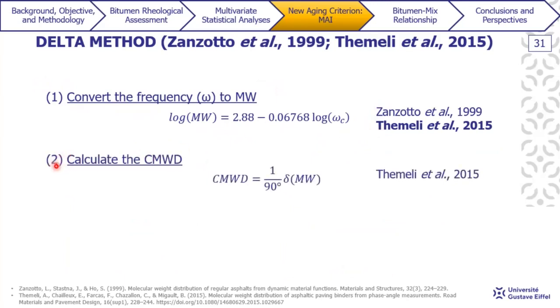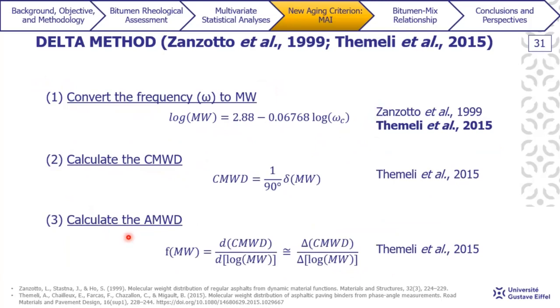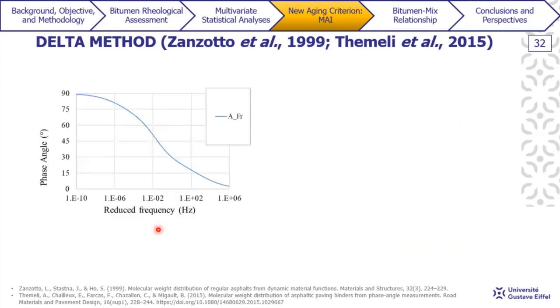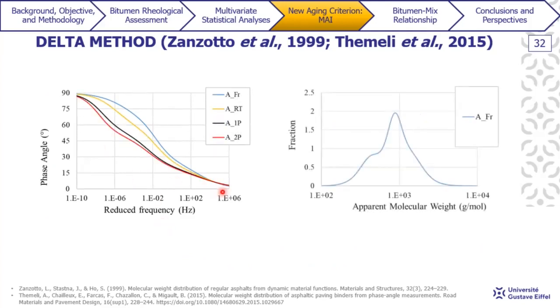Then we calculate the accumulated molecular weight distribution, because the delta method considers that the phase angle master curve is proportional to the cumulative molecular weight distribution. And then we take the derivative of the cumulative molecular weight distribution to get the apparent molecular weight distribution here. Just to illustrate what this apparent molecular weight distribution looks like, here I have again the four aging levels of bitumen A. And when I use the delta method, here is what happens.